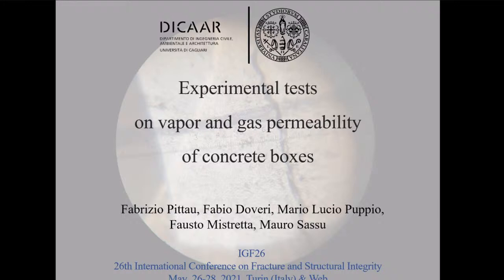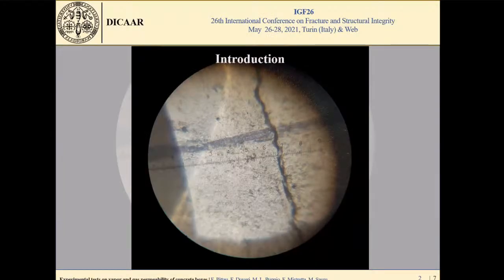Good morning, everybody. Who speaks is Mario Lucio Puppio, and together with other colleagues from the University of Cagliari, we present this first step of experimental tests on vapor and gas permeability of concrete boxes. This picture shows cracking of a concrete wall. This cracking depends on the natural property of concrete, and is measured with an instrument, a micrometer, that allows an estimation of the crack. As you absolutely know, cracks are the primary path for external agents that produce degradation of both concrete and reinforcement. It is also the main cause of concrete permeability, particularly for gas and vapor.